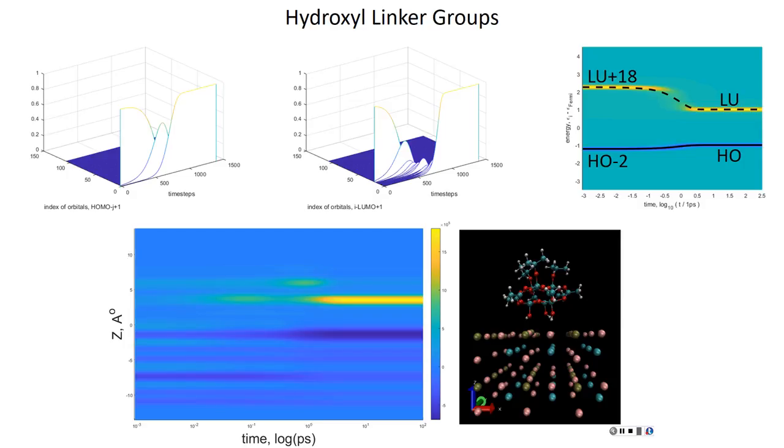Yeah. But I think the main conclusion is that this ligand layer on titanium dioxide, which you call linkage or something like this, definitely affects differently both the charge transfer, the speed of formation, how to say, the quickness of formation of the state with charge transfer character, as well as overall relaxation times. And it looks like they also affect electrons and holes differently.